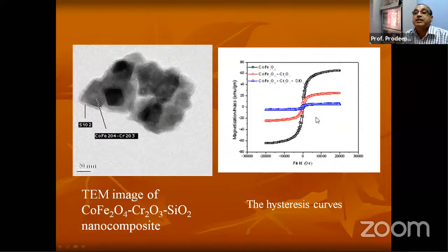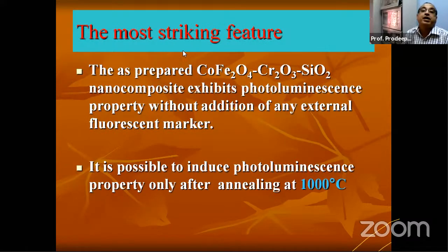And these are magnetic hysteresis curves. In this case you see here, simple cobalt ferrite is very highly magnetic. Then this oxide, it is magnetic. So magnetic property decreases when you modify the surface of the catalyst. This is an important and interesting observation we made. Once the surface is modified, the magnetic property decreases. Still, we want a catalyst which can be separated using an external magnet, so that much magnetic property is sufficient for us.